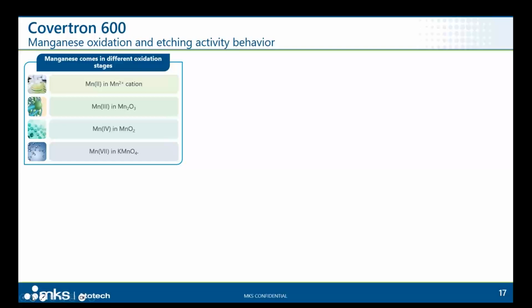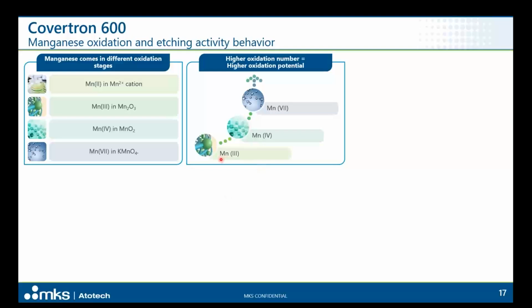This element, you know, comes in different oxidation states, from manganese 2 to manganese 7, and in the middle you have manganese 3 and manganese 4. With a higher oxidation number, the oxidation potential of the manganese chemistry is higher. So we go in this direction, with manganese 7 being the highest oxidation potential that we can achieve. With the Covertron 600, only this state, manganese 7, is the active species that works for etching. So the Covertron 600 works with a permanganate to be active for etching.